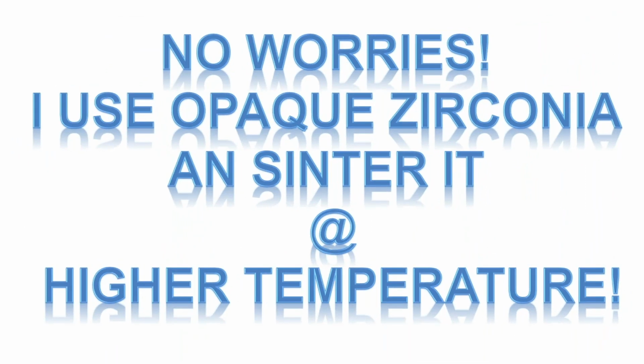We also have to make sure, like I mentioned, that we get calls that say, well, I have this certain zirconia or certain sintering furnace, and I just throw everything in at the same temperature. I want more translucent zirconia, so I'm going to increase the temperature. By increasing the temperature on the sintering, you do have an enlargement of grain size, which allows more light transmission, so it will be more translucent. That is true. However, it really doesn't work that way as far as strength. You've compromised the actual material. So you probably have about a 20, 25 degree high-low before things get out of whack. But you have to make sure that you follow the instructions again.